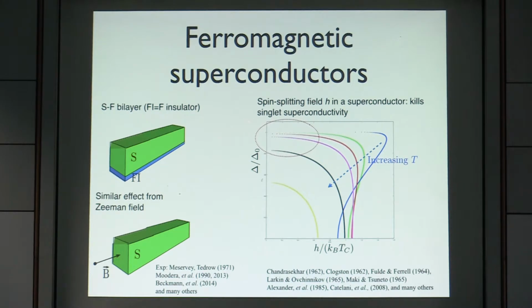At low temperatures you get this curve, where you have a branch with multi-valued delta. But basically you see that eventually, by increasing the exchange field, you kill superconductivity with large exchange fields. But before you do this, you almost do nothing to delta. This is physics that was studied already in the 1960s, first by Chandrasekhar and Clogston. There is also this interesting Larkin-Ovchinnikov-Fulde-Ferrell behavior that happens roughly there. In my talk, I will mostly be in this parameter regime of the red circle, where I'm assuming that almost nothing happens to superconductivity, to delta.